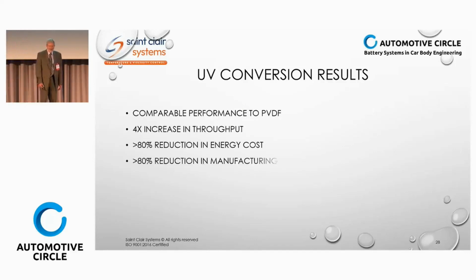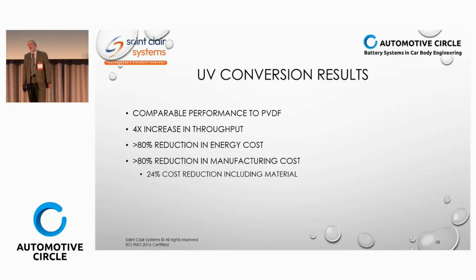But here's the money slide, okay? Converting from standard thermal cure PVDF to UV resulted in no loss of performance, 4 times increase in throughput, over 80% reduction in energy cost, over 80% reduction in manufacturing cost. And when you combine that manufacturing cost with the materials involved, it reduced the cell cost by nearly 25%.